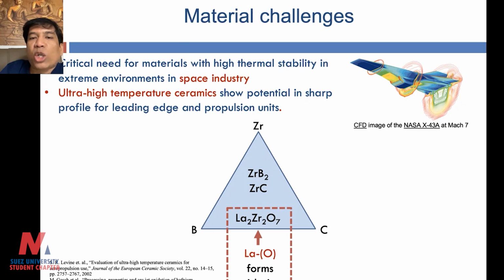So we have been working on non-silicon based materials. As you see here, we have been working on rare earth based ceramics. And the whole challenge here is to make these ceramic coatings; we don't use ceramics directly. What we do is make polymeric precursors where in the backbone of the polymer, we have all the elements that are required to produce the high temperature ceramics like zirconium boride or zirconium carbide.